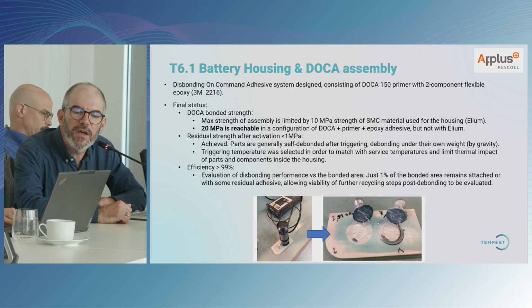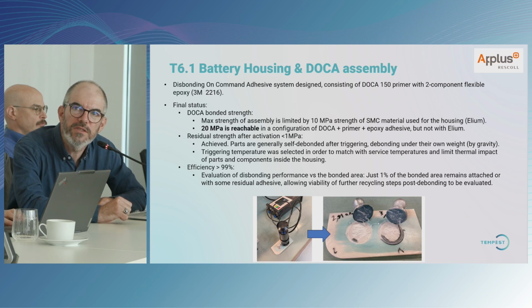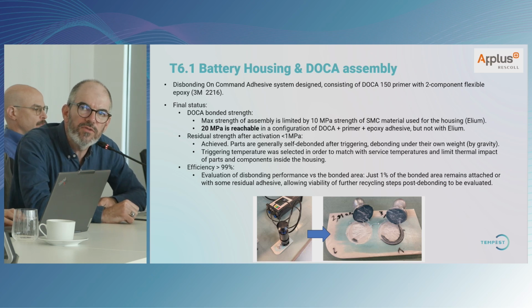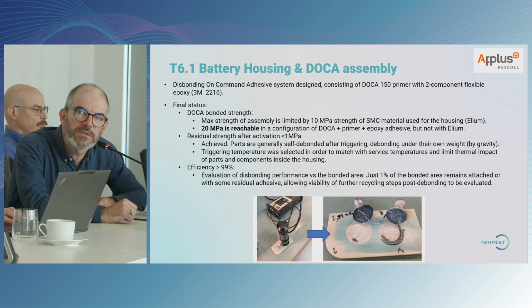For this specific project, we used a debonding primer, which is triggered. The name within the project is DOCA 150 because it triggers in the range of 130 to 150 degrees C. And this primer was combined with a 2-component flexible epoxy, 3M 2216, for the bonding of housing components.